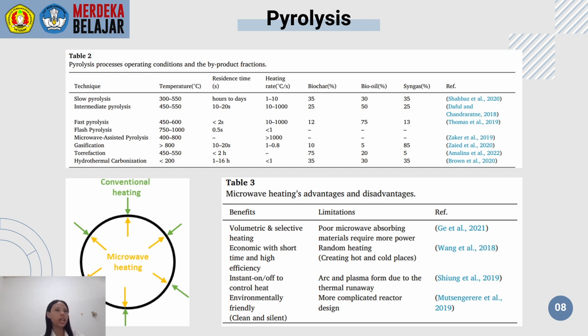Biochar yield is often less in fast pyrolysis because only primary char is produced. Due to the unavailability of secondary reaction, the whole process of fast pyrolysis is endothermic. Fast pyrolysis recommends biomass containing less than 10% moisture content by weight to reduce water in the final bio-oil. In addition, the low moisture level allows the feed to be ground into fine particles to enable rapid heating and pyrolysis. Flash pyrolysis aims to optimize bio-oil production.